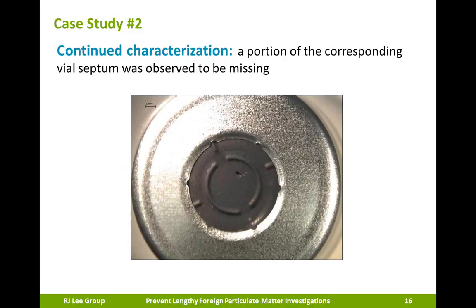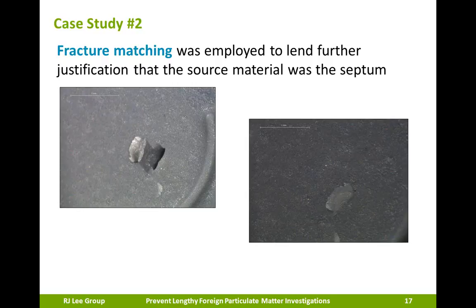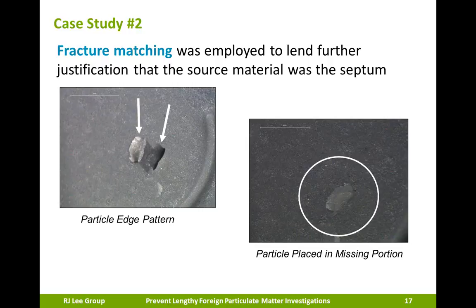It was noted that there was a missing portion of the vial septum. The company did indicate to us that the septum had been punctured with the syringe needle, so this was consistent with the piercing. We transferred the original particle and utilized another forensic technique known as fracture matching. And the particle was oriented into the void. As you can see at high magnification, the particle edges lined up with the void. So essentially the particle fit in like a puzzle piece.